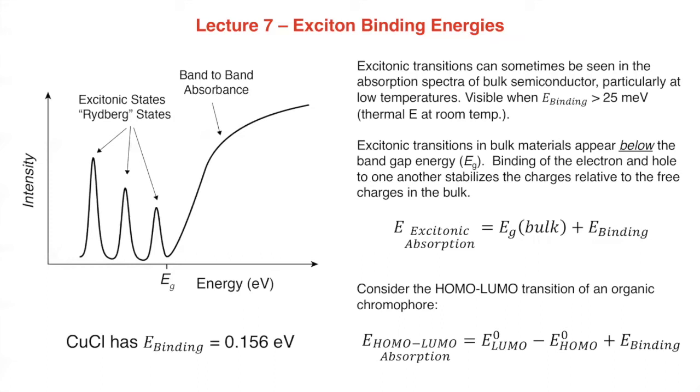All right, so that's a pretty big difference and it has a really big impact on the way materials behave. I didn't show this slide last time, but it's just a reminder here, clarification. On the left, I've shown an absorption spectrum for an excitonic material. Now, this is meant to be a bulk material. And so an example of such a material is copper chloride. Copper chloride has a pretty large electronegativity difference. It has relatively weak bonding, and so small bandwidths, and as a result, the binding energy of the electron and hole in the exciton is large and the Bohr radius is small. And so you get something that's really got a Frenkel exciton in a bulk crystal.